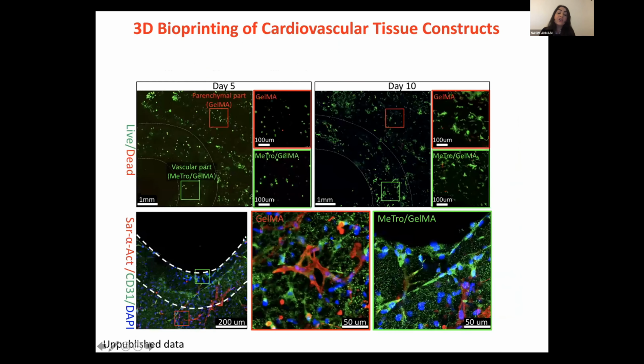And here are some data showing the viability of the cells that we incorporate in different parts of the construct. This is the vascular part formed by our elastin-based biomaterial, showing that the cells are viable, and also in the surrounding matrix where we incorporate cardiomyocytes and cardiac fibroblasts, we observe high cell viability. We also, similar to the previous in vitro testing, did a staining for different cardiac markers and also for CD31 to ensure that the cells that we incorporated to form this scaffold are all functional, and also have the right phenotype.